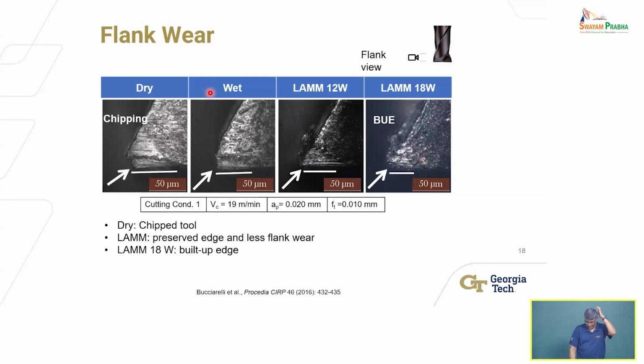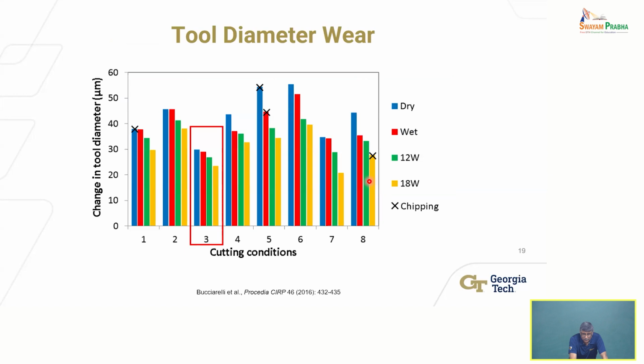All right. So you can see here what the tool looks like. This is looking at one edge of the tool, focusing in on an optical microscope. You can see under dry conditions, the tool has chipped. The sharpness is gone, right? And this is under wet conditions. It's a little better, but it's also worn quite a bit. This is with laser assist. Not bad. It's still maintaining its sharp edge. There's some material sticking with higher laser power, softer material. It's going to adhere, etc. So that is to be expected. Not ideal, but expected. This is showing you change in tool diameter because of wear.